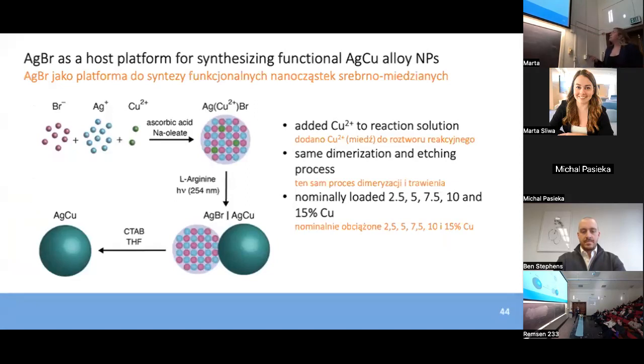So we did so by simply introducing copper cations into the reaction solution to form these silver copper bromide hosts. Those silver copper bromide hosts underwent the same dimerization and etching process that I've described so far, forming silver bromide silver copper dimers. Then we can isolate the silver copper alloy nanoparticles from that system, again, by selectively etching away the silver bromide phase of the dimer.